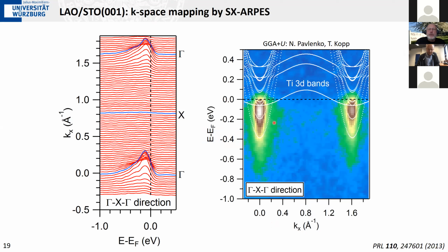When they have a much richer fine structure in their band structure, which is due to the quantum well states that form in the potential trough on the strontium titanate interface side. In our experiment, we do not have the resolution to resolve all these fine details. That's the price we pay by going to these higher photon energies, where so far we do not yet have the same experimental resolution as in low energy photoemission. But nonetheless, you can clearly track the existence of these electron pockets.